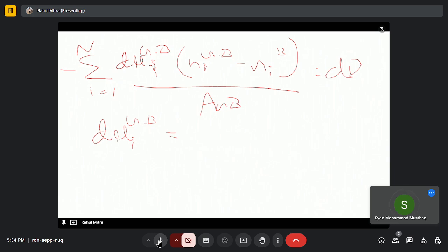Because we are writing for B, let's assume the activity of the i in the phase obeys Henry's law. We know Henry's law: the activity of any component, if it is a dilute solution, will be equal to a constant times the mole fraction of that i in that solution. So let me write it more clearly.